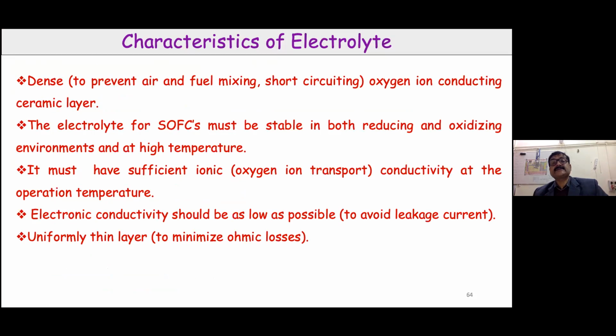Now, as I said, it contains electrolytes and not only electrolyte, but the electrodes also. So an electrolyte is the major component of any fuel cell. The electrolyte should be dense, of course, to prevent any short circuit between the electrodes. It should be stable, both in reducing and oxidizing environment. It must have sufficient ionic conduction so that the oxygen ion can move from the cathode to the anode. So it has good oxygen ion transport. It should be an oxide ion conductor instead of an electronic conductor, and electronic conduction should be as low as possible in order to avoid any leakage current. And a uniform thin layer is required.